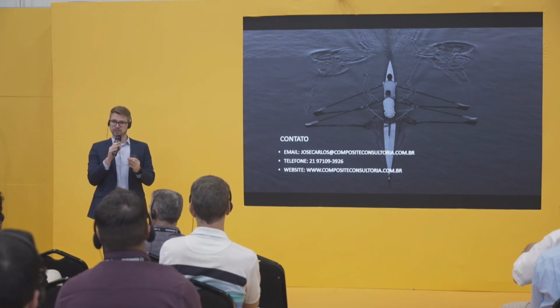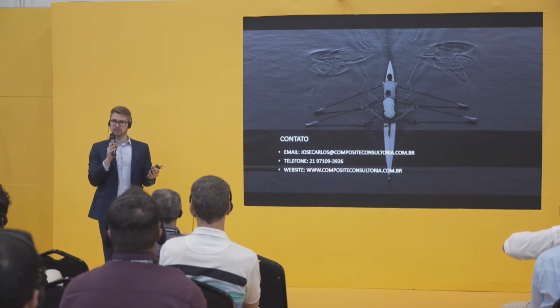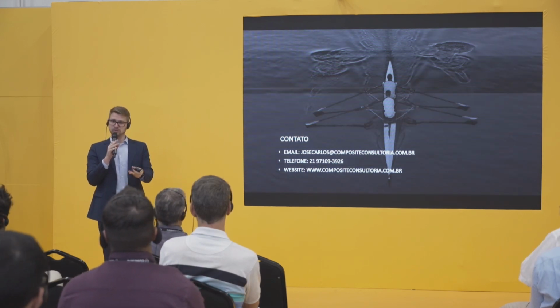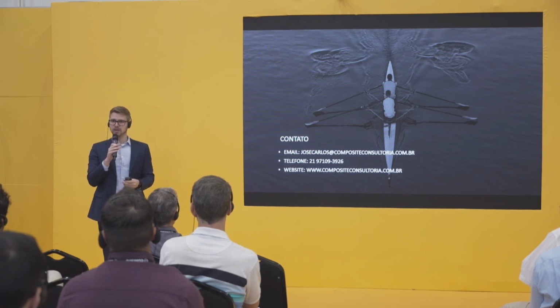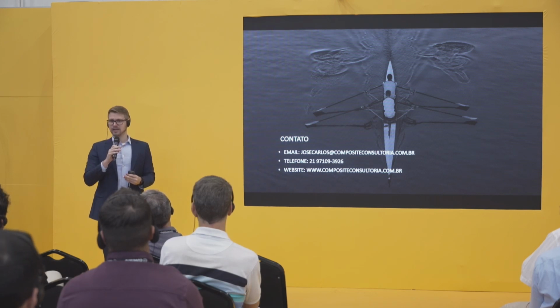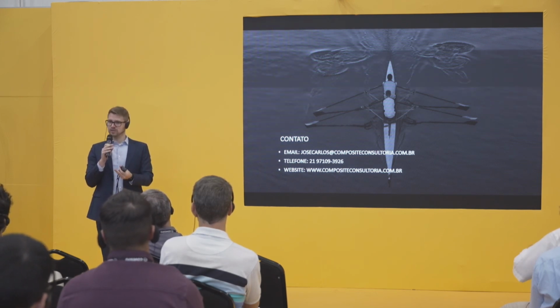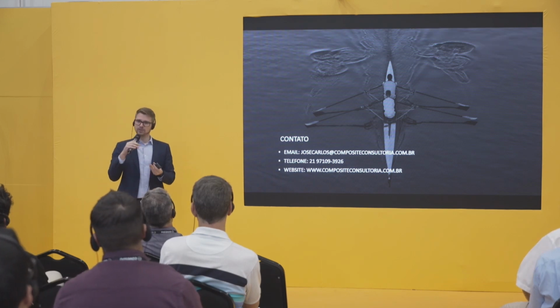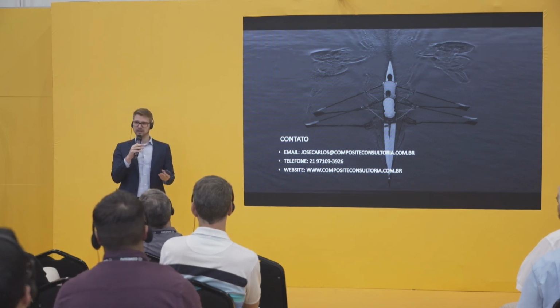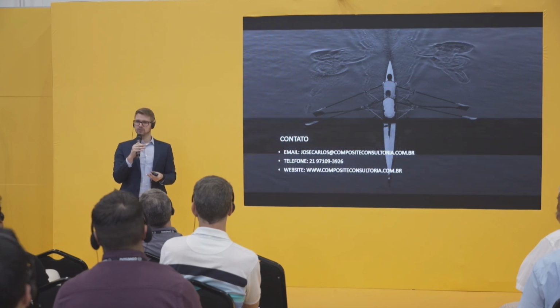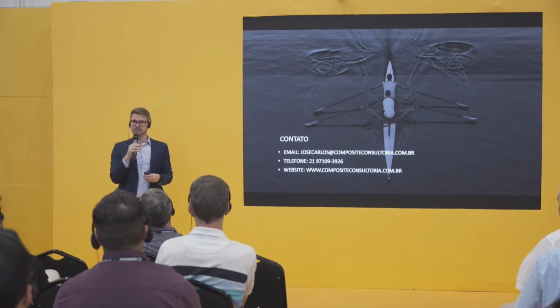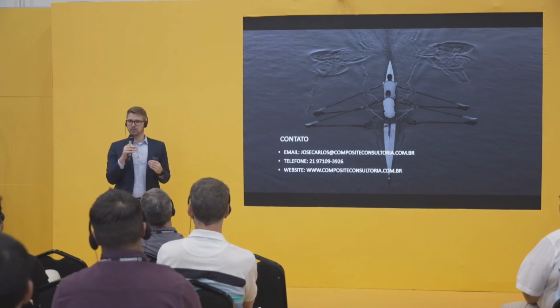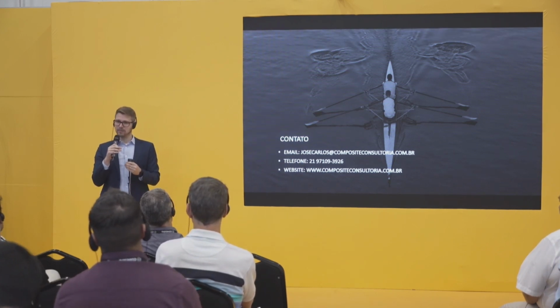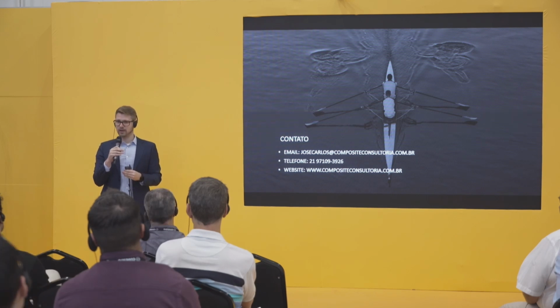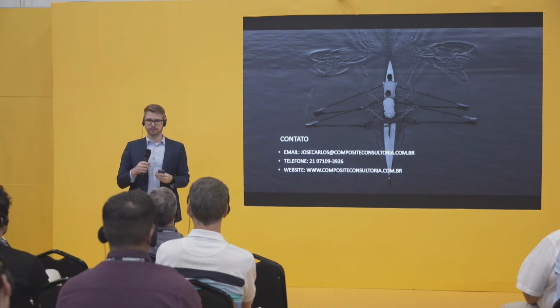So we use the leftovers to do this bit on the side or in the center, depending on the type of infusion. But the permeability of glass and carbon is very low, poor, because when we do a sandwich, the foam needs to have grooves, or when it's solid, we have to use an infusion screen to increase the permeability of the laminate. The pure laminate, only the glass fiber will stop that because there is low permeability.